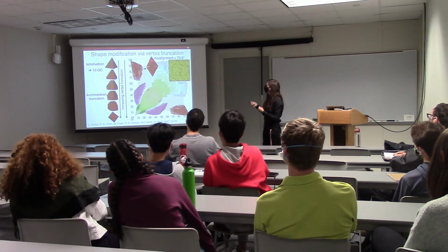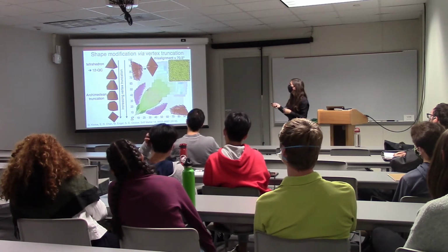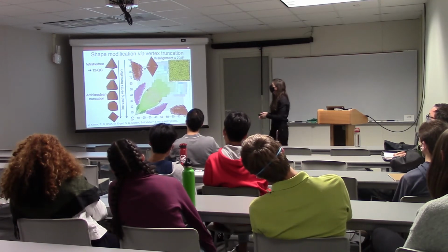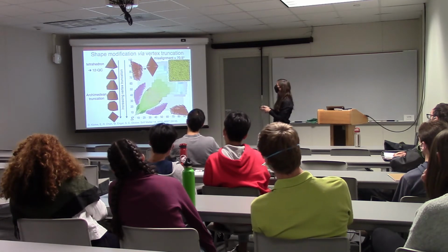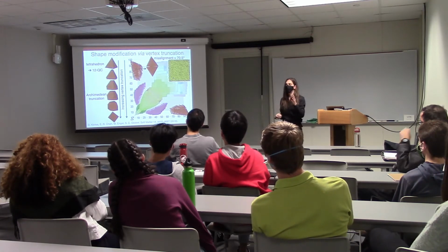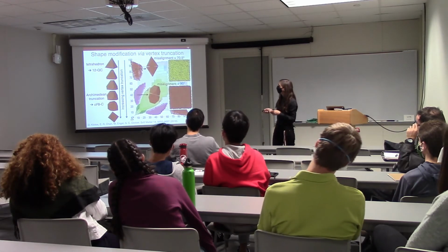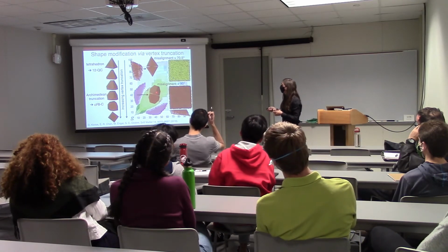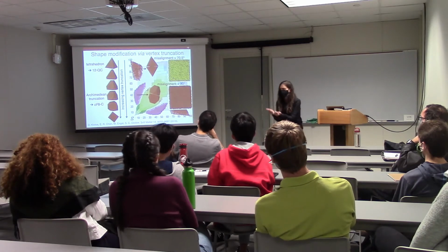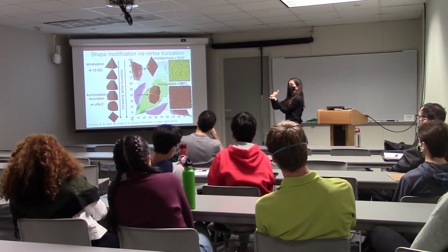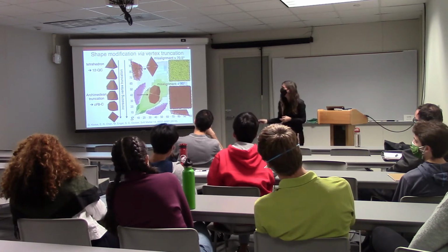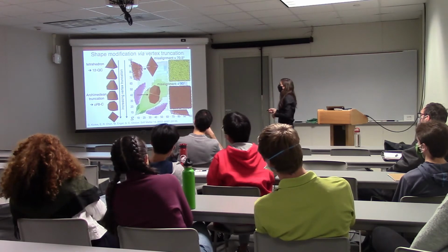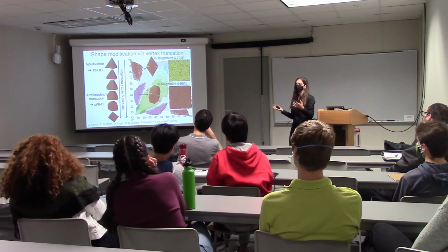The tetrahedra have this overwhelming motif of a misalignment that we measure to be around 70.5 degrees. That's transferring the orientation of one tetrahedron to the neighboring one with the minimum angle, a 70-degree rotation. Whereas the Archimedean truncated tetrahedra form a diamond-type crystal structure, where another misalignment of 90 degrees is prevalent. It's not with a mirror, but with an inversion point, that's how they relate to one another. In between, you have this range where the motifs are competing and frustrated.